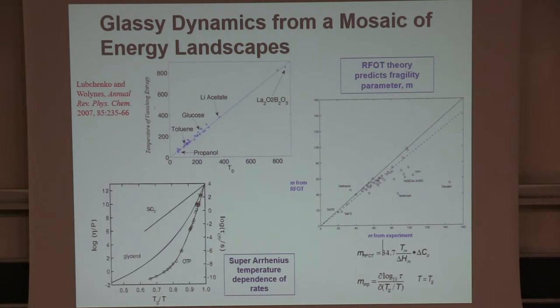OK. I would say that you have to be a very strange person to say that this is not convincing, that there's something like entropy driving the transition. You can argue there's something else going on, maybe to give you some deviations here. There's a few points that are really odd, but if you're a chemist, these don't bother you much. Decalin here is a material that, when it melts, it still rotates in the molten phase. Similarly, selenium, when it's undergoing the transition to becoming an amorphous material, is also polymerizing. So in general, this is a really quite strong correlation.